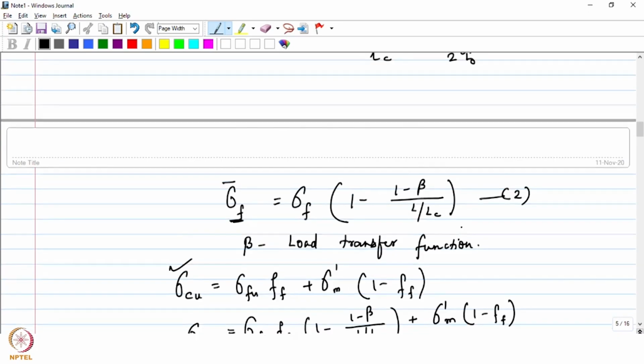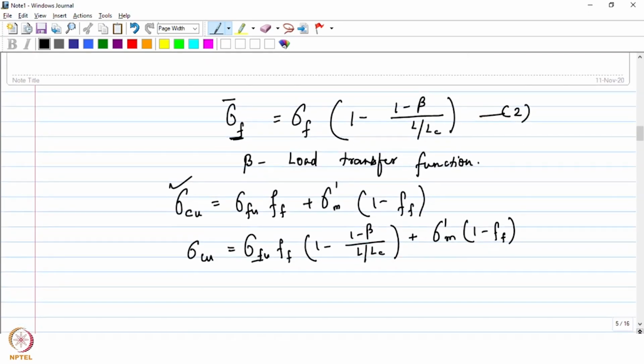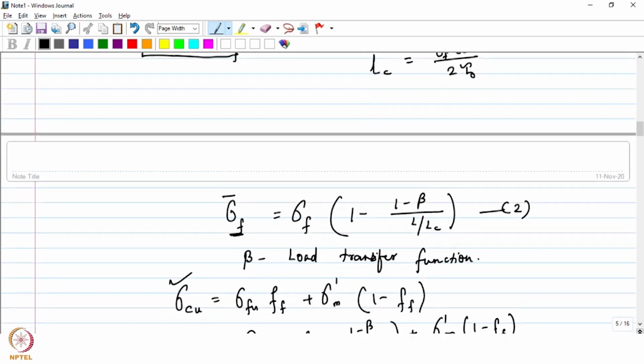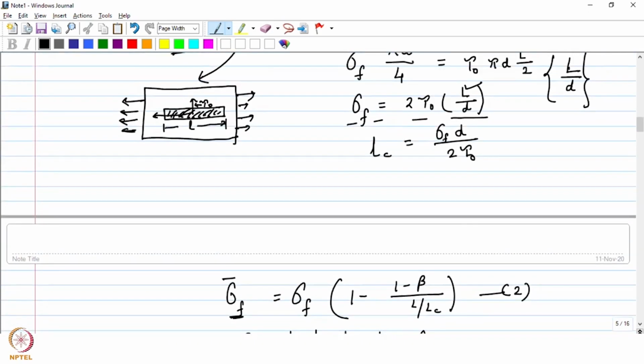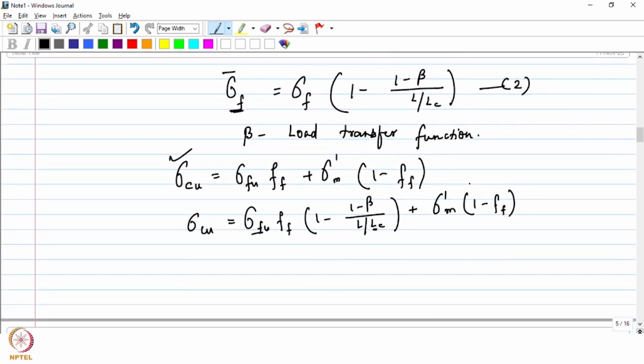So from here, you can see that the discontinuous fibers with a smaller length will always produce less strengthening than continuous fibers, okay? Because here it is there in the denominator, right? The L by D. LC contains the D factor, as you could see from here, right? Sigma F by tau 0 is nothing but a dimensionless parameter, a dimensionless number. So L by LC basically represents L by D, right? So when L is small, you can see the strength of the composite will be lower.